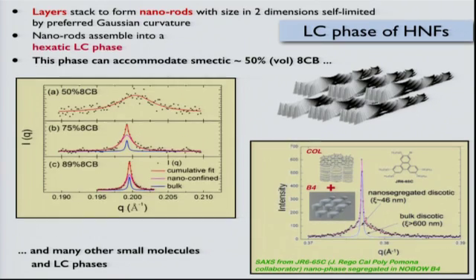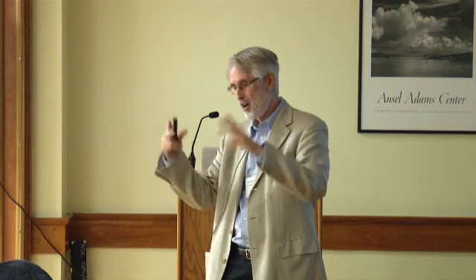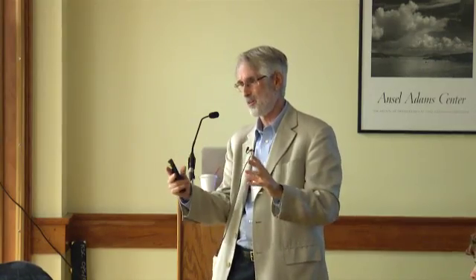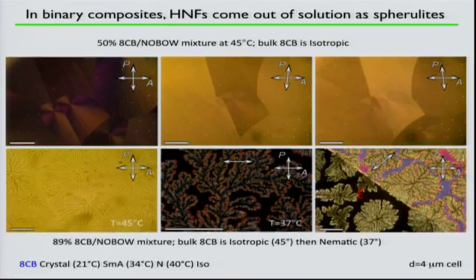It looks like 8CB in an aerogel. And the helical nanofilament, if you go to higher concentrations, it starts to bulk phase separate. So the helical nanofilament phase can somehow accommodate about 50% by volume of almost any guest. And so here, you still get the conglomerate. This is this mixture of 50% 8CB and NOBOW, and you can see right-handed and left-handed domains. You uncross the polarizer and analyzer, and then you rotate the polarizer the other way, and this starts out dark, gets bright. So the 8CB is in there.